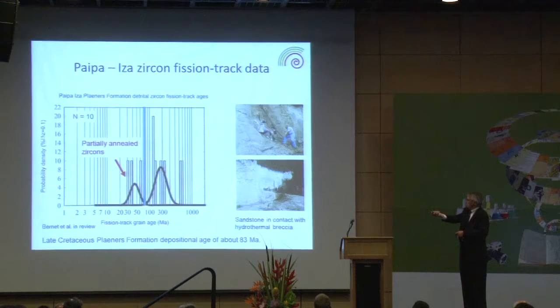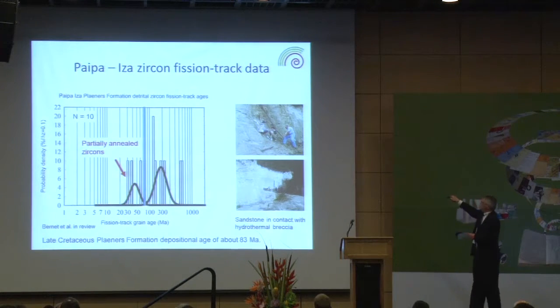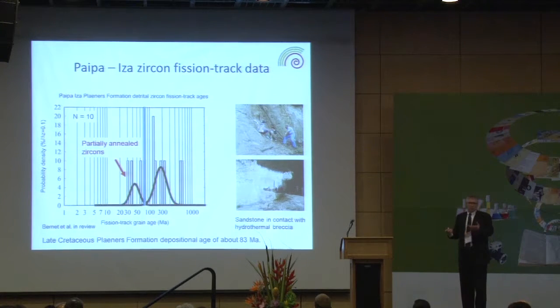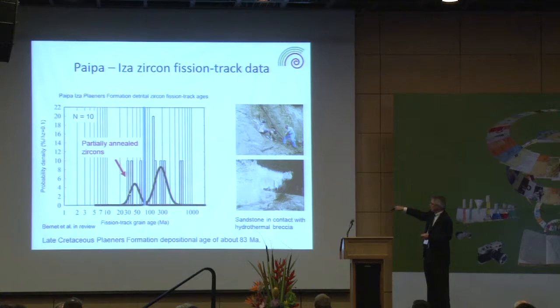So why do we say this? Well, for this one sample that we have from the Plaeners Formation, we got a meager 10 grains. I know this is not sufficient to really represent the age distribution, but because the separation of the ages is so clear, we're still going to exploit this sample, even if it's very poor with 10 grains. But we get a young peak here, which is at about 50 million years, and another one that's about 300 million years, sorry.